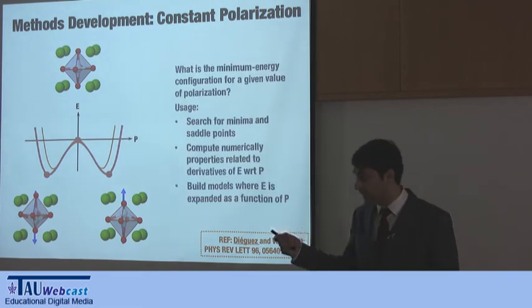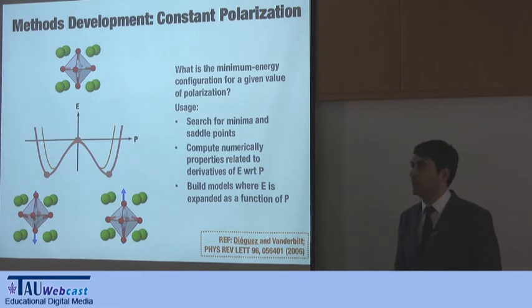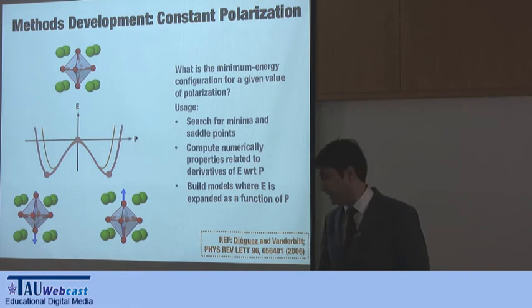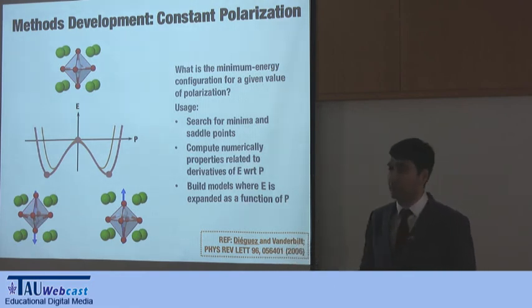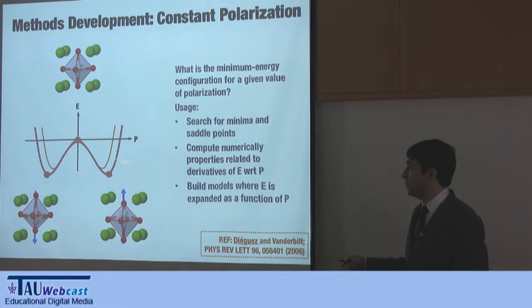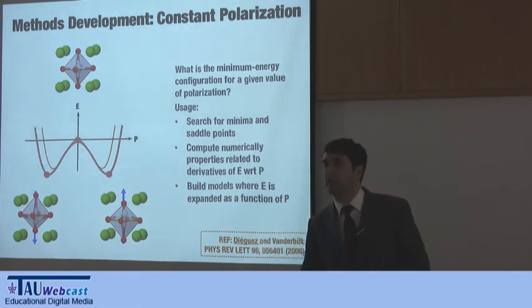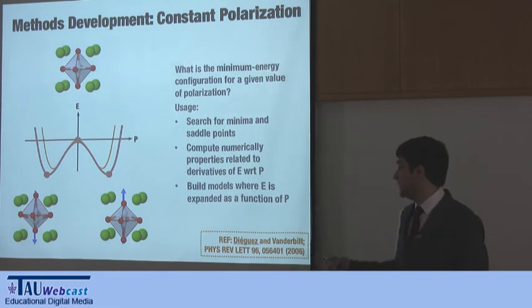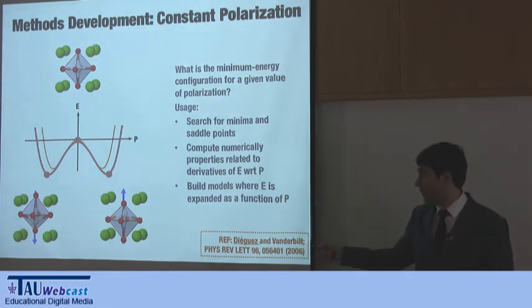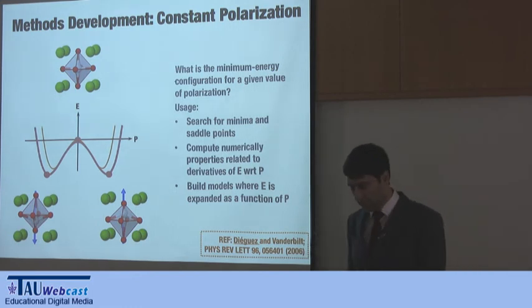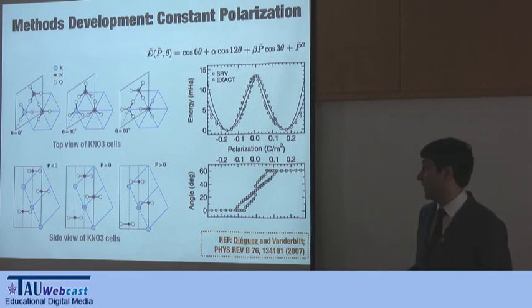And well, why would you do that? For one reason, because it will help you to search for metastable states that might otherwise be hidden if the surface is complicated. You can compute properties of the material that are related to the derivatives of the energy versus the polarization, like the dielectric constant, which is basically this curvature. So if you have the curve, you can get the dielectric constant. And if you are building effective potentials or effective Hamiltonians, you can use the polarization as a variable, and then you have a map of the energy versus the polarization, so you can fit this expansion.